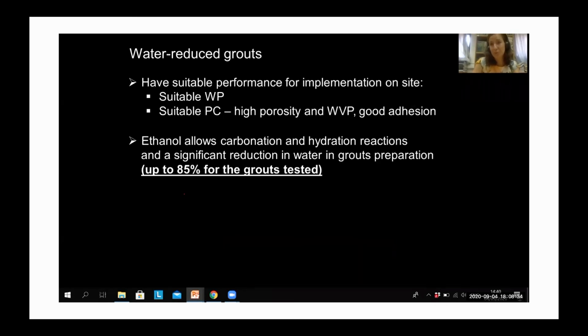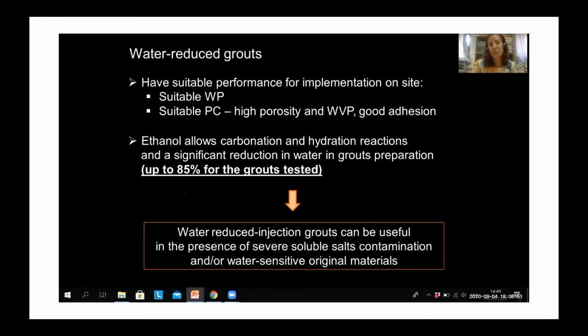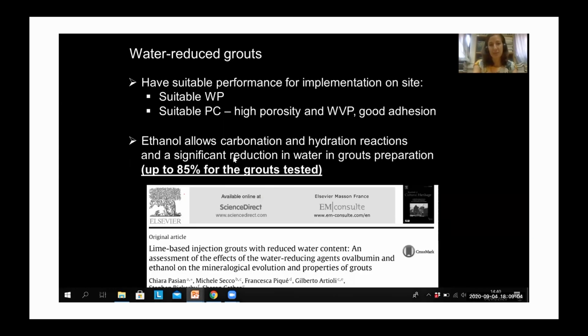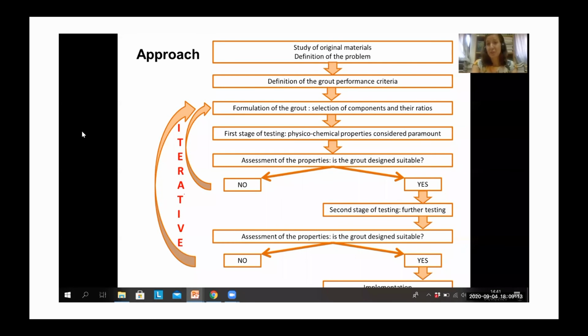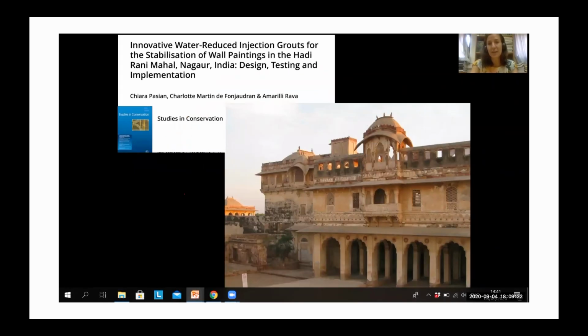And also important to note that ethanol allows carbonation and hydration reactions that was verified, and a significant reduction in water in grouts preparation, as we saw, 85% for the grout tested. So the conclusion was that water-reduced injection grout can be useful in the presence of soluble salts contamination and or in case of water-sensitive original materials. And if you're interested, this is a publication with more information. So this is the general approach in terms of injection grout design. And if you're interested, actually this was applied during a conservation project by the Courtauld Institute of Art in Nagaur in India. And this is a publication which is in the IIC preprint.